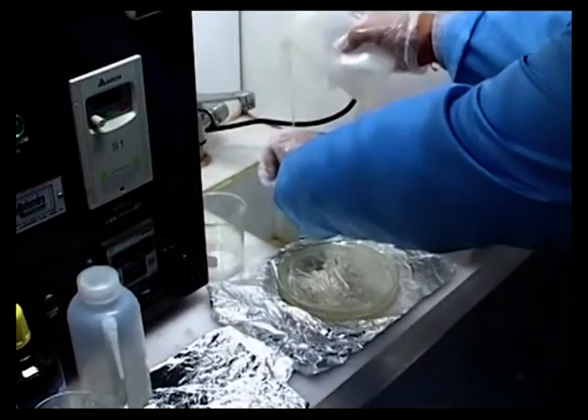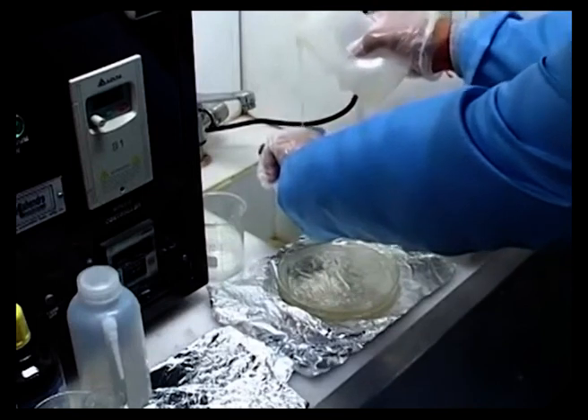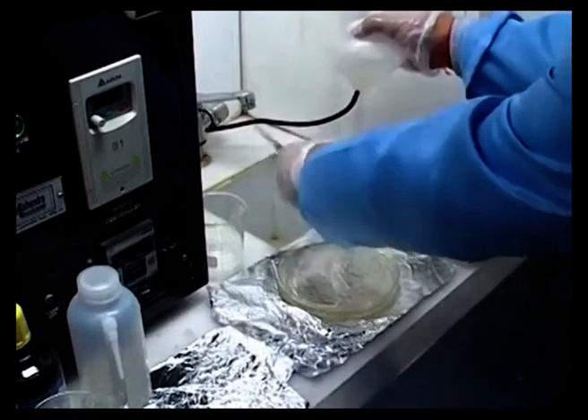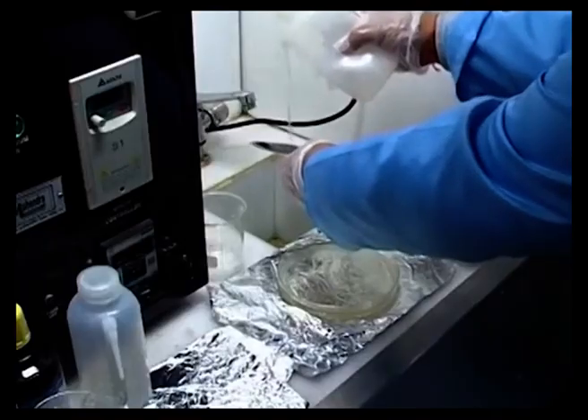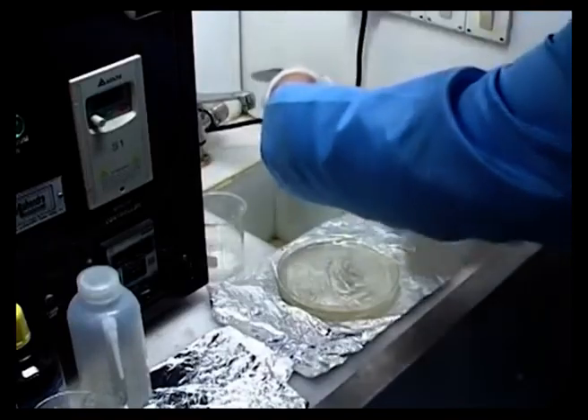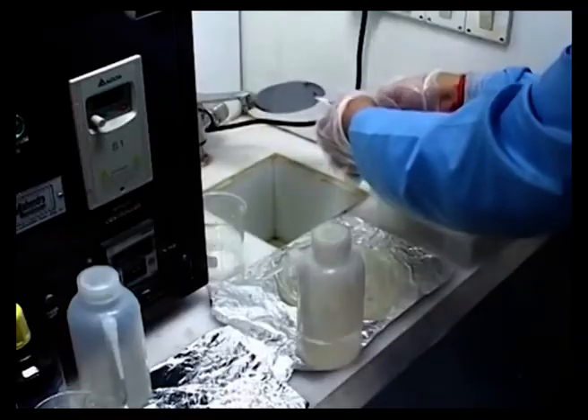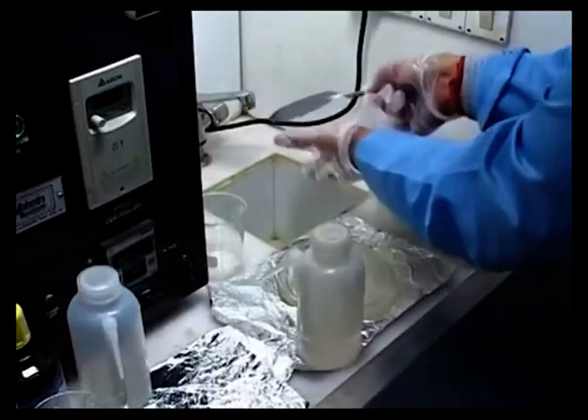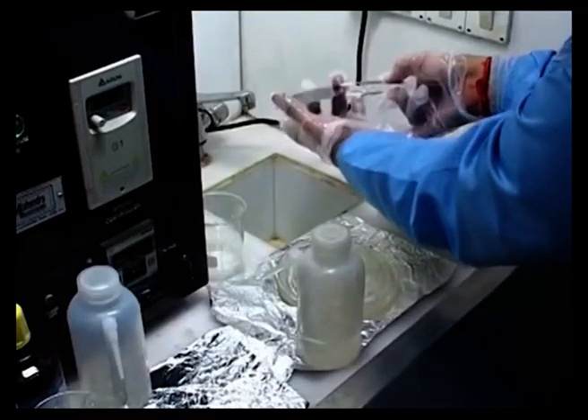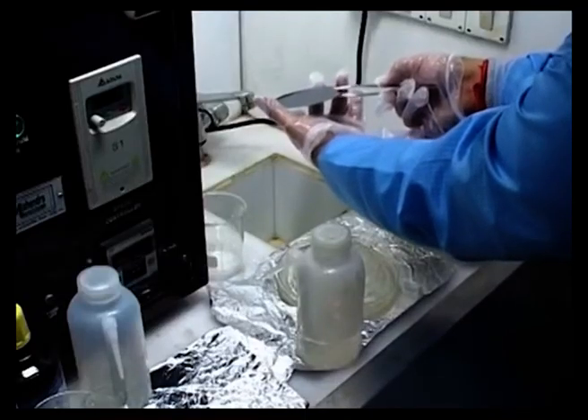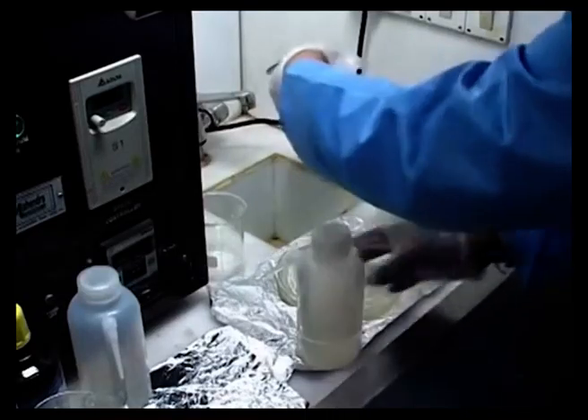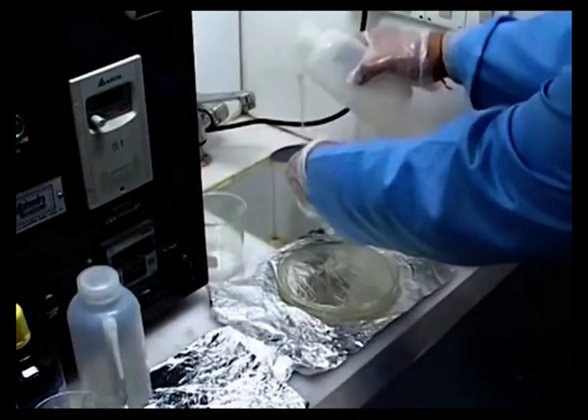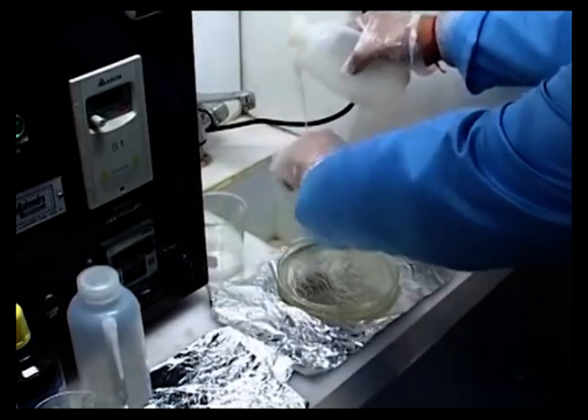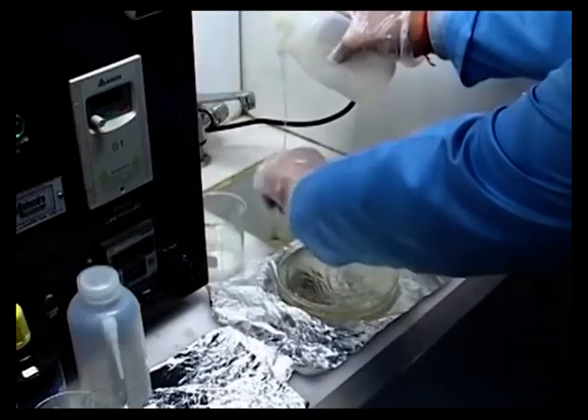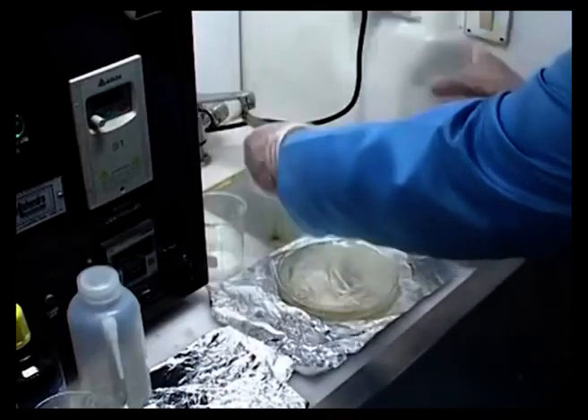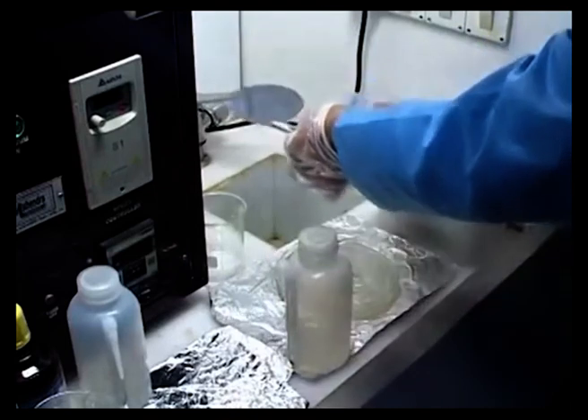As you can see here, this is actually a squirt bottle which is squirting away the DI water on the top of the silicon wafer. So essentially, after completely rinsing it, you basically try to just change its holding location to a different area, so that you can rinse off the acid in the particular area where it was held before, and this way you can clean the whole sample. And essentially you can see now that the sample is more or less thoroughly cleaned, thoroughly washed, and it has a super clean nature on the surface.